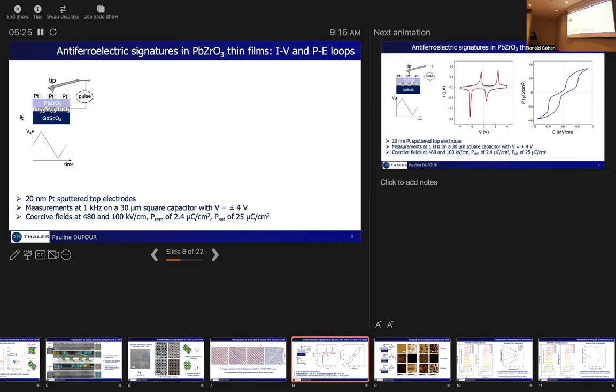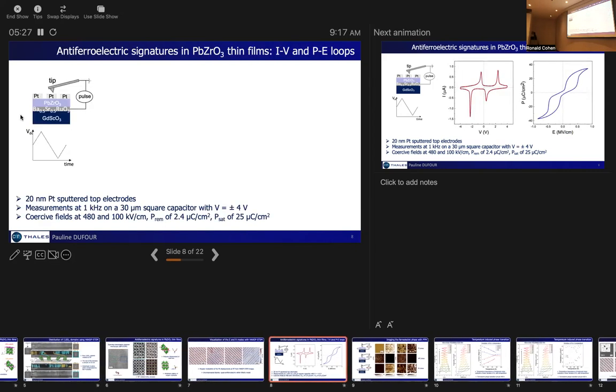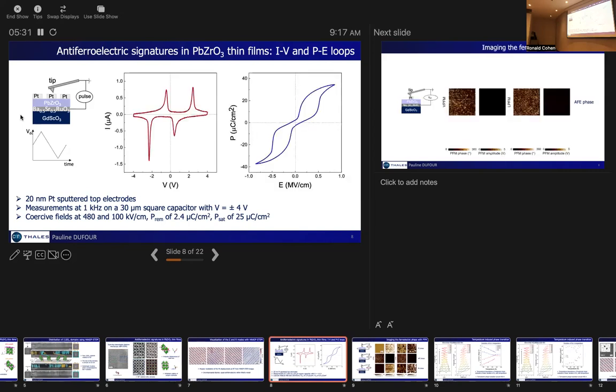Now we want to probe the electric field-induced phase transitions. So we performed electrical measurements at 1 kilohertz on 30 micron square capacitors, and we observe very clear electrical properties characteristic of antiferroelectrics, with on the IV curve four switching peaks corresponding to the antiferroelectric to ferroelectric transitions and to the ferroelectric to antiferroelectric transitions, which gives you this very characteristic double hysteresis loop. So it seems that electrically our films are fully antiferroelectric.